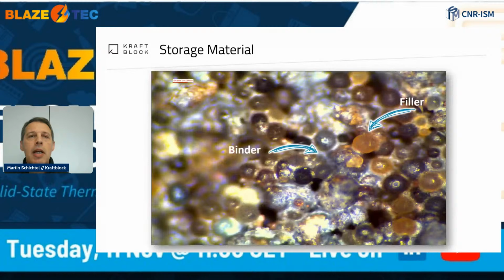Good heat capacity in sensible materials usually means worse heat conductivity. But if I want to run a technical process very fast with low latency, I need very strong conductivity as well. As we mix a strongly conductive, phosphate-based binder with capacity fillers that have good capacity, we can balance out what we prefer. Do we prefer more heat retention? We reduce the quantity of the binder. If we need a fast cycling system, we increase the binder slightly in order to charge much faster and discharge much faster. And that's basically seen in this microscopic view, right?